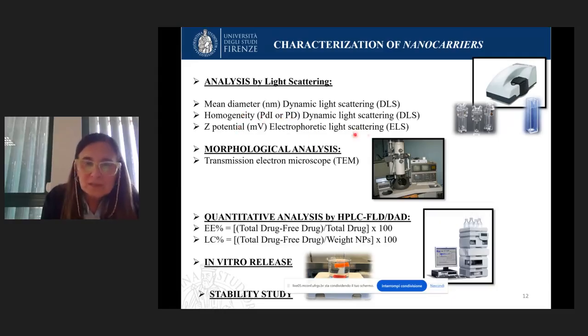By electrophoretic light scattering, we define the zeta potential, the charge present around the particles. A high charge, positive or negative, and a high potential around the particle are important to stabilize the system and to guarantee the stability of the colloidal dispersion. The morphological analysis is performed with the transmission electron microscope and confirms the DLS data: the shape, the aggregation of the nanocarriers, and the dimension of nanocarriers.